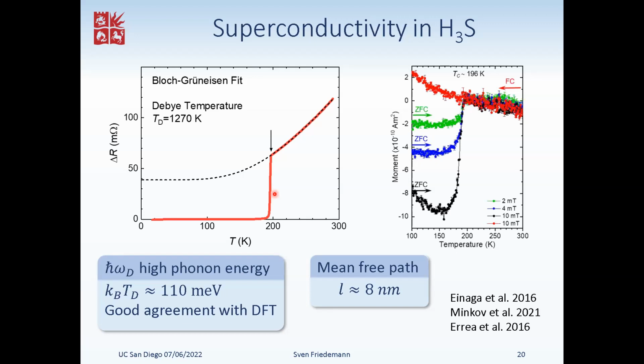And what are the difficulties of going to the next stage, to the yttrium hydrides? Or the difficulties of pushing this up to room temperature? So the lanthanum hydride, LaH10, is what was the record before the carbon sulfur hydrogen work, and yttrium H10 has a very similar transition temperature, both around 260 Kelvin. They have the difficulty that you can get multiple phases.